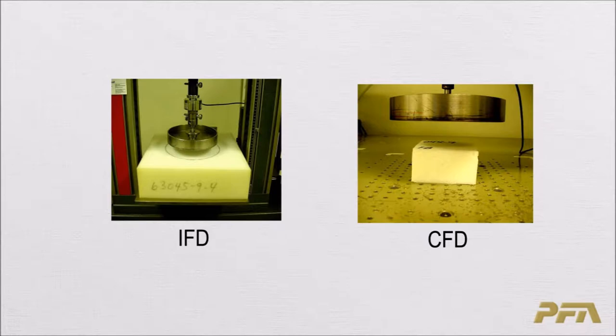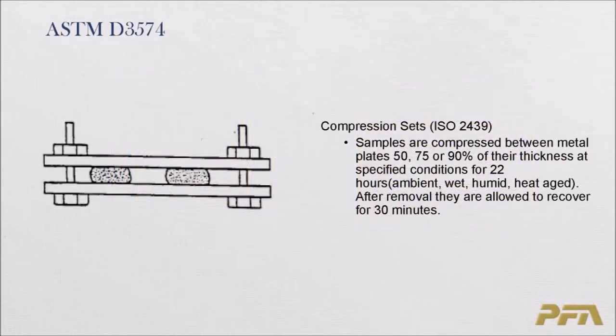IFD is thickness dependent while CFD is independent of thickness. The next test is compression set, where a sample is compressed between two metal plates to a specified deflection — either 50%, 75%, or 90% — for 22 hours. These conditions can be ambient or at some aging condition: either wet age, humid age, or heat age.